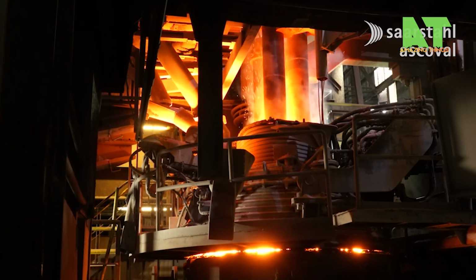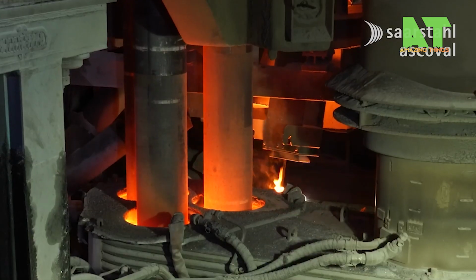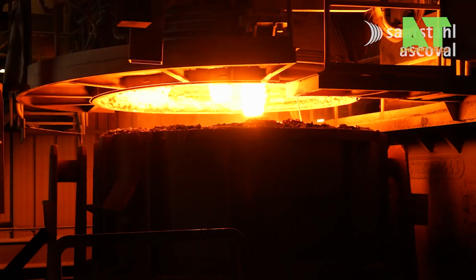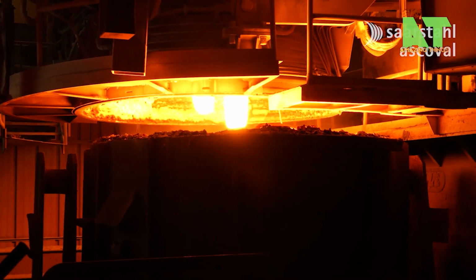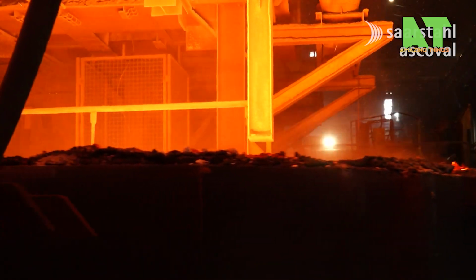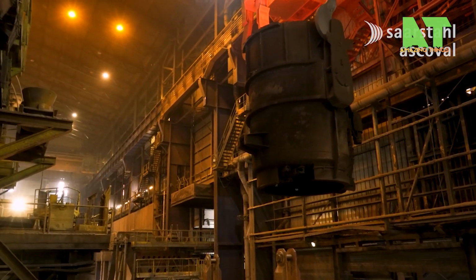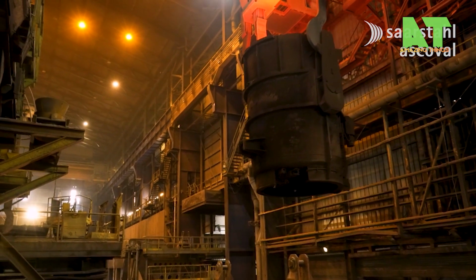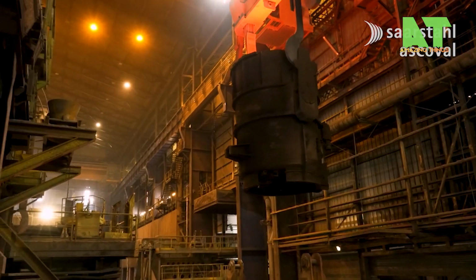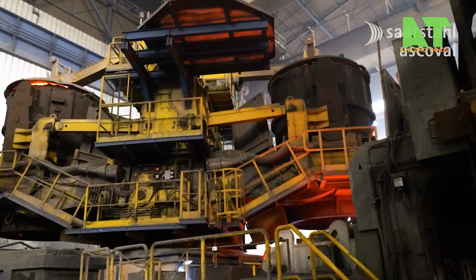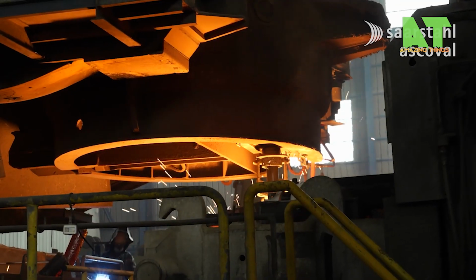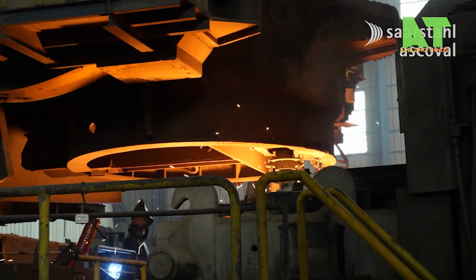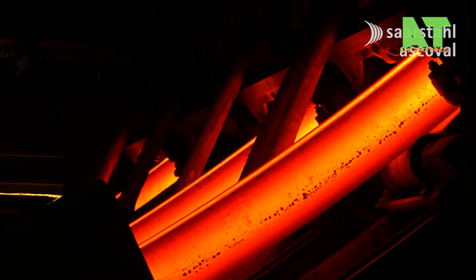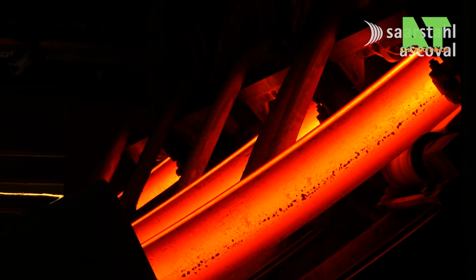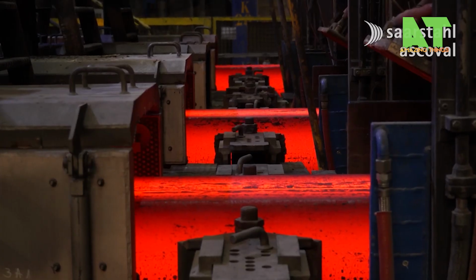From the ladle, the steel moves to the continuous casting machine. This is where liquid metal becomes solid bar stock. The molten steel is poured into a water-cooled copper mold that shapes it into a round billet. As it moves through the machine, a series of water sprays cool the outer shell while the core remains liquid, a delicate dance of heat and physics. By the time the strand exits the caster, it's a solid round bar, glowing amber, ready to be cut to length by a flying shear.